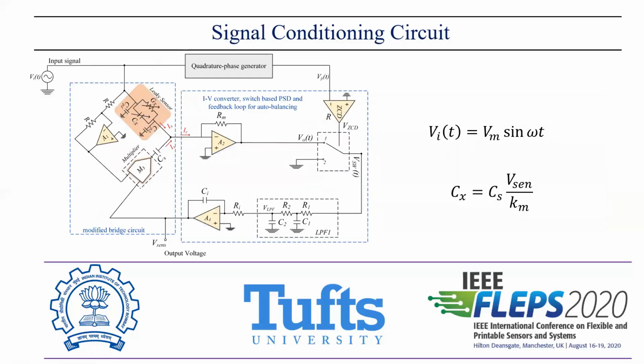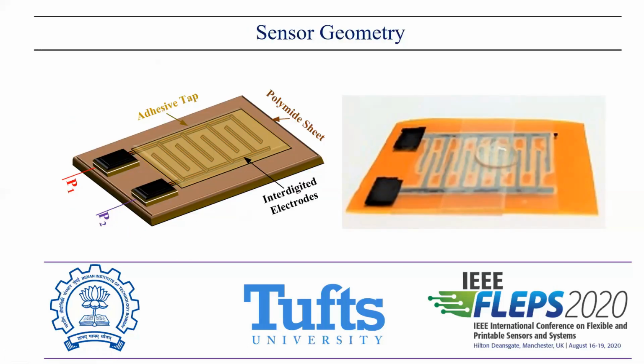So now we can see that the sensor contains a layer of interdigital electrodes around it, and of course the measurement is a conductive liquid or soil moisture. So the conductance between those fringing fields, or basically we can say the leakage resistance between those fringing fields, will also change. Between those interdigital electrodes it will also change according to the measurement.